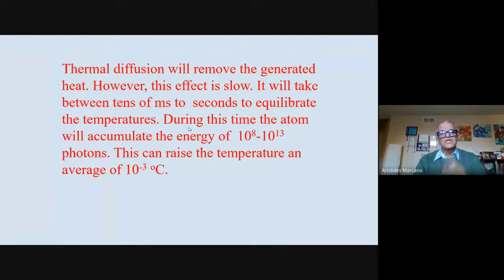It means that that single atom can accumulate the energy of 10 to the 8, 10 to the 13, so trillions of photons. It means that on one single atom, it works like it's absorbing the energy of 1 trillion photons. And that's the basic thing that makes that method very sensitive. And the point is that this single microliter of water will raise the temperature, the average temperature, by 1/1000th of a degree. As we will see, this is good enough that we can detect this kind of change in the temperature. You don't need a sensitive thermometer, but you detect that using this photothermal method we're going to talk about.